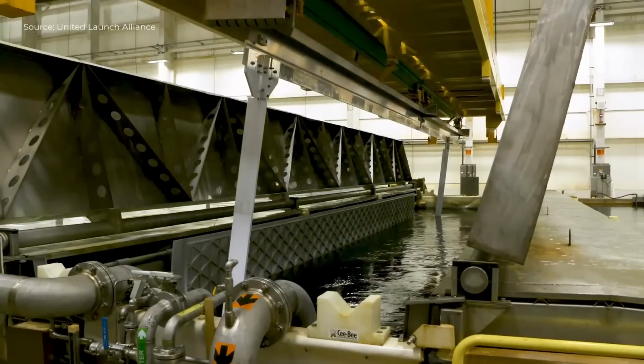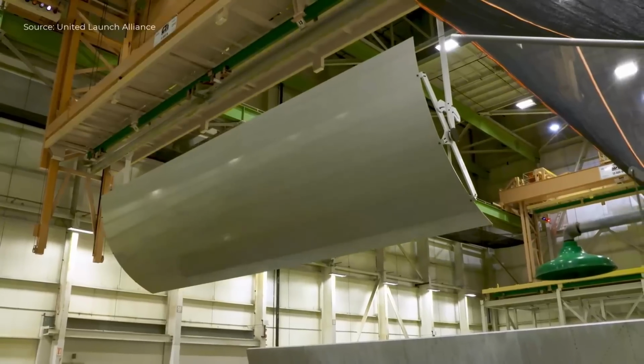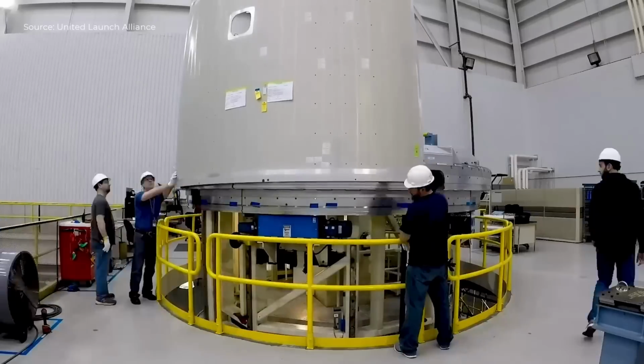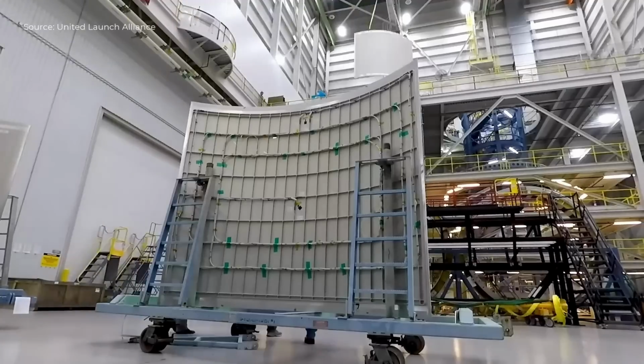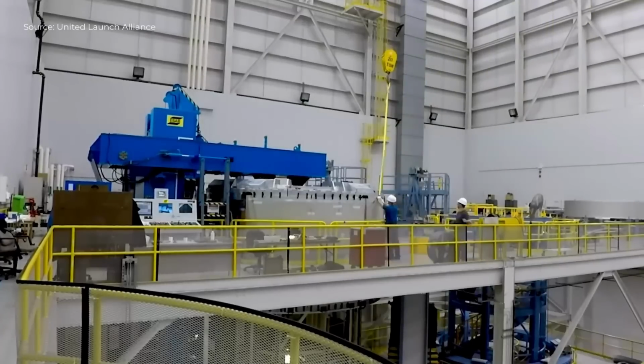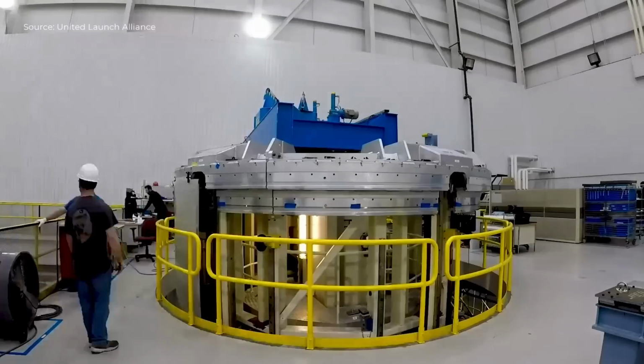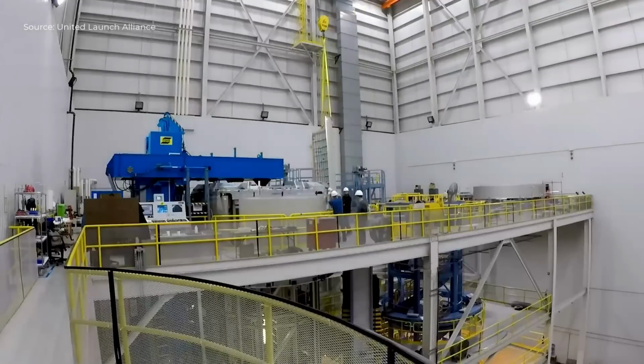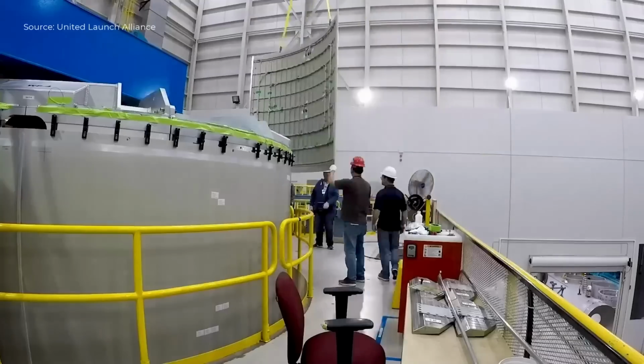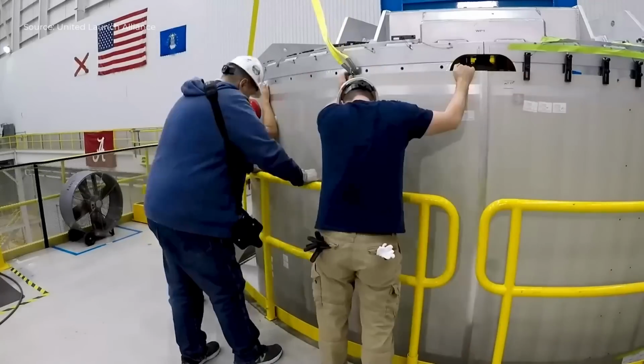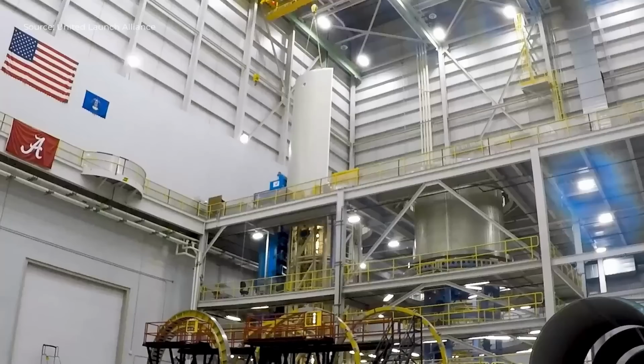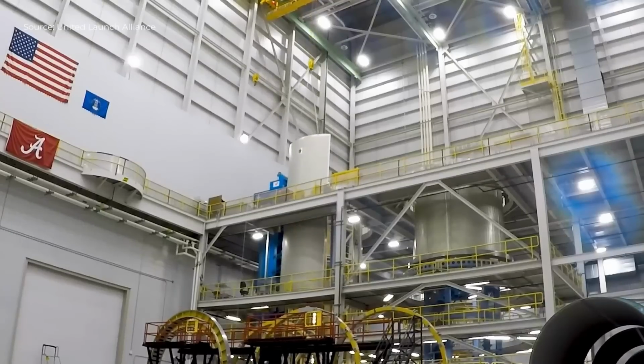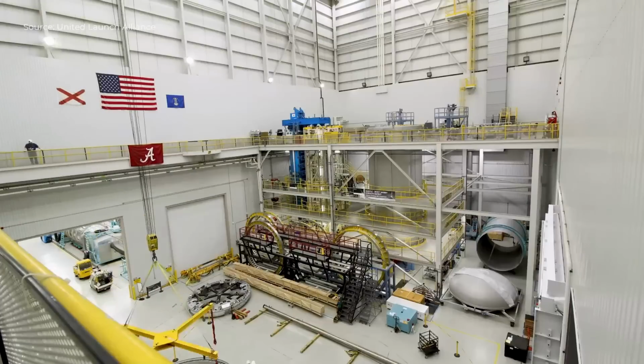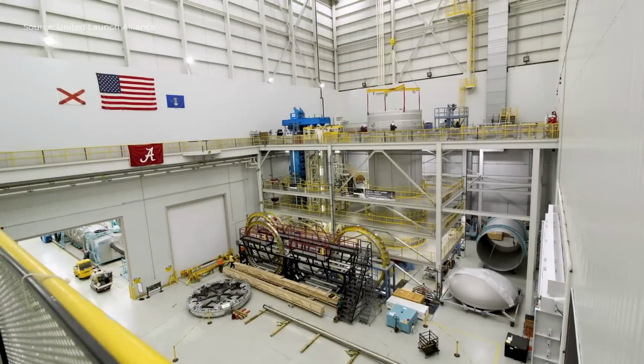Construction starts with large aluminum plates milled by double gantry skin milling machines, reducing weight by 70% while preserving structural strength. These panels are formed into curved sections through brake forming and bump pressing, then anodized for corrosion resistance. The panels are friction stir welded into barrels, a solid-state process using frictional heat without filler material, creating exceptionally strong joints.